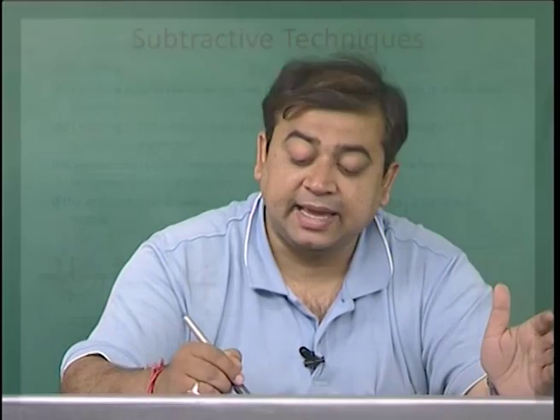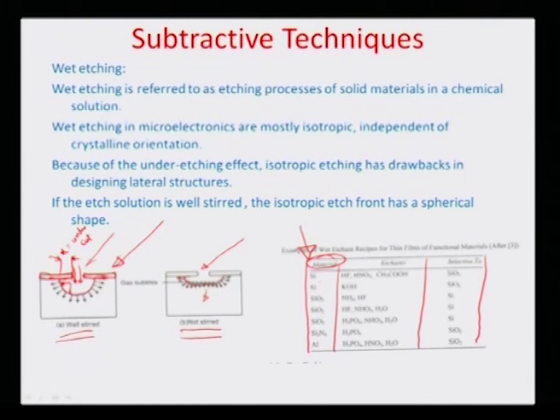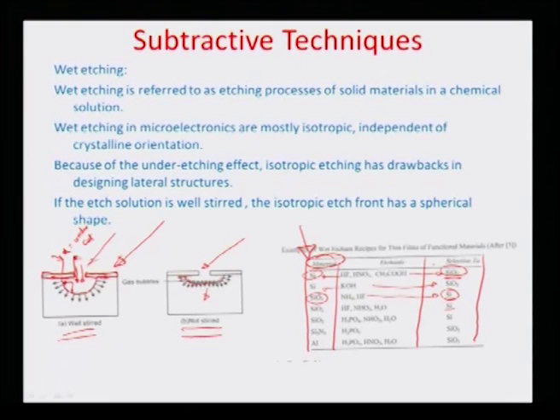So, let us look at this table again. The materials illustrated can be silicon, silicon dioxide, silicon nitride, aluminum, and so on. And then there are etchants which are amenable to removal of these materials, for example, HF, HNO3, CH3COOH, or for example, KOH, which can remove silicon very easily. But as soon as the etchant meets a surface of SiO2, it is selective to SiO2, so it will not etch SiO2 anymore, or it will not etch Si anymore in this particular illustration, where NH4F and HF combinations are used. So there are certain etchants which etch away one material and are selective to another, for example etching away silicon while being selective to SiO2. The combination of these can be used for a variety of etching architectures that can be realized accordingly. Thank you.